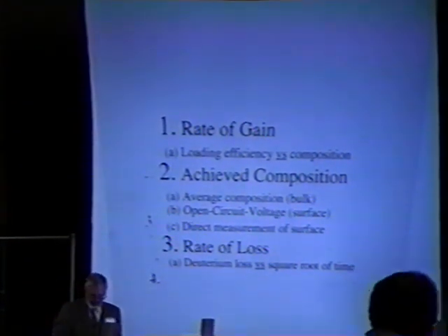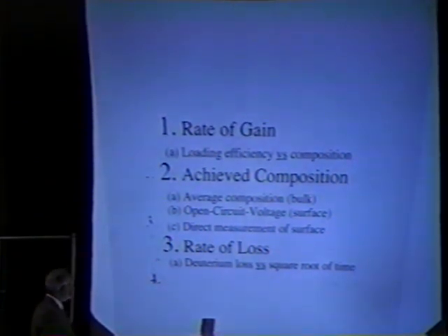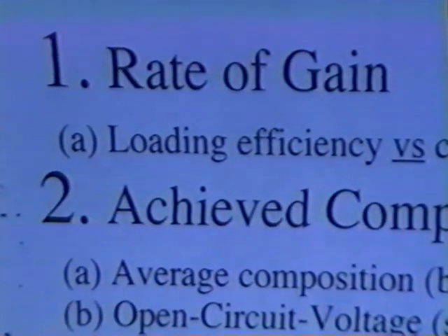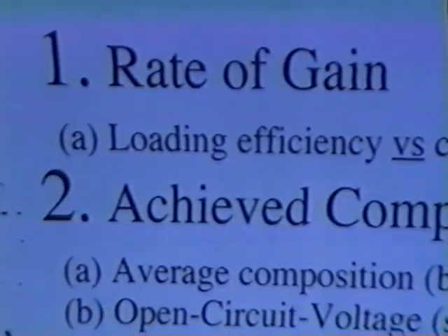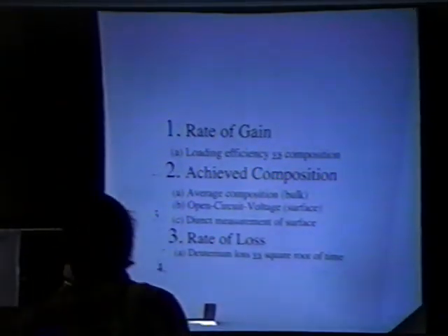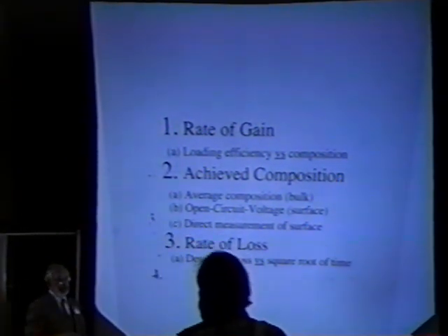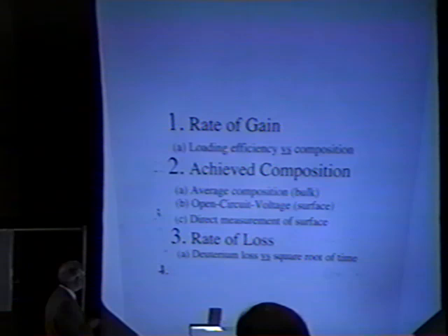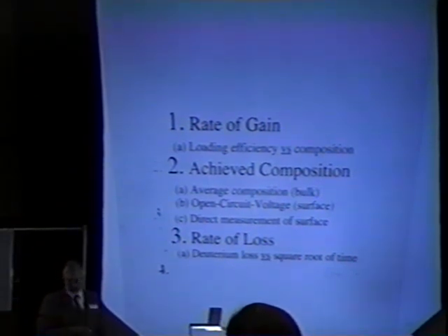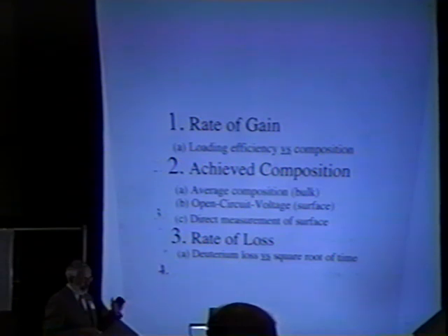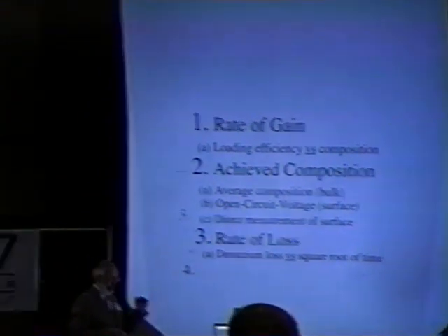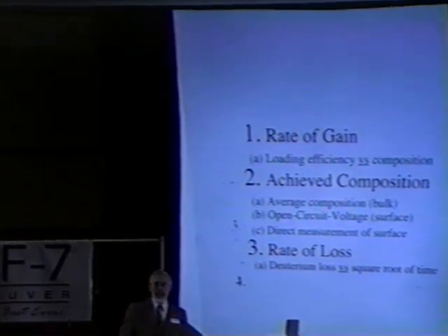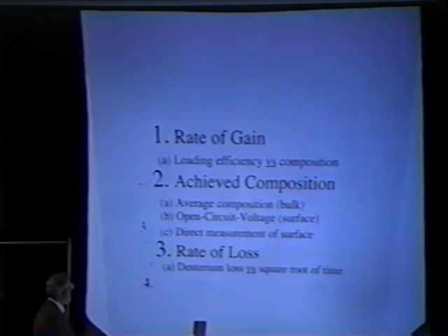It's necessary, as we all know, to obtain a high composition. The composition is obtained by the competition between the rate of gain and the rate of loss. These two are separate independent properties and need to be determined separately and independently. So I have looked at the rate of gain and measured that in terms of the loading efficiency, which is the ratio between the number of atoms of deuterium that are going into the palladium divided by the number presented to the palladium by the current at any particular time.